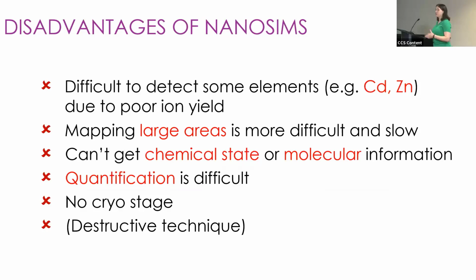The NanoSIMS is not perfect, and there are certain things we can't do with it. It is difficult to detect some elements, namely things like cadmium and zinc, simply because we don't get enough secondary ions from these elements. It's not a technique to map over large areas. This is very time consuming. So the NanoSIMS really is a technique for looking at small regions at high spatial resolution.